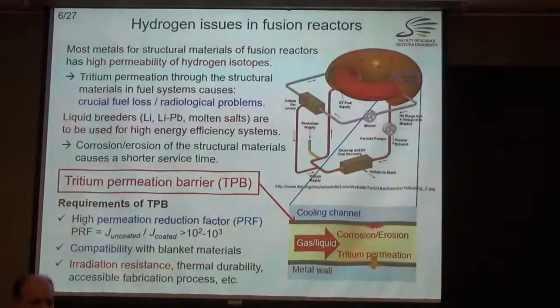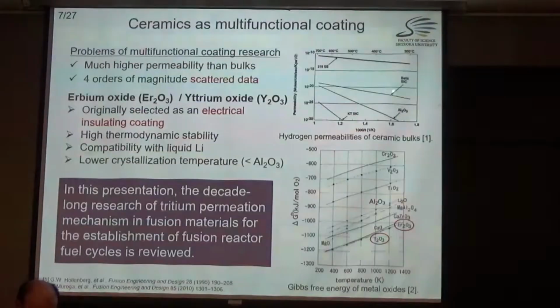So the history of the coating development is it was using basically aluminum oxide or silicon carbide or something like that. And the problem was that the permeability was much higher than bulk when it was coated with a thin film. So something is wrong with the thin film. Then the data is scattered, by orders of magnitude, so it's a factor of 10 or 100,000 or something like that. So that's a serious problem.